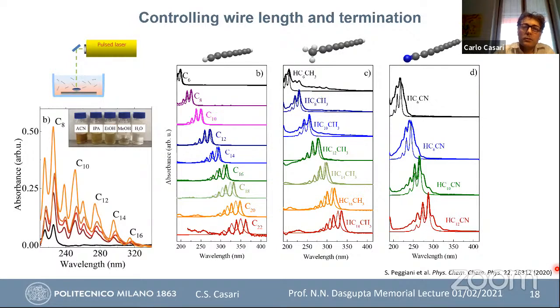And this is an example of what we do by pulsed laser ablation in liquid in different solvents, including water. Depending on the solvent, we can see different yield of formation and even type of termination. For example, in acetonitrile, we have the formation of hydrogen terminated polyynes. These are all single-triple bond structures, terminated by methyl groups, or terminated by cyano groups, CN, coming from the acetonitrile, so from the solvent. And these are all lengths from 6 to, for example, 22 carbon atoms observed, and by comparing the experimental data with the theory, we are able to distinguish and recognize this kind of structure.